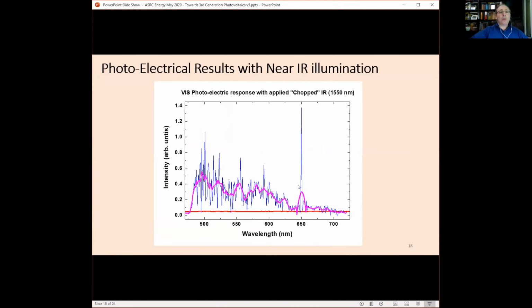Here's the result of measurement of observation of absorption in visible part of spectrum when we shine infrared light at 1550 nanometers, which is much below that absorption layer. And you can see that quantum dot sample, it's not the greatest results.